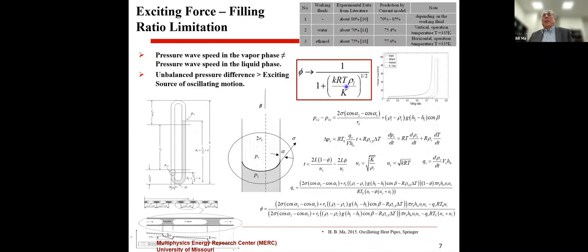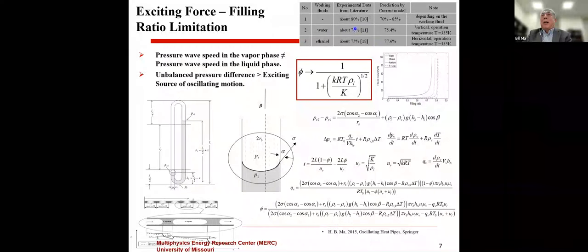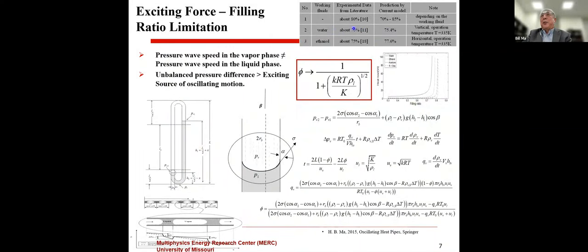What that means is that from here we can find the filling ratio limitation. Based on this equation, we can predict, for example, for a water heat pipe, if the liquid ratio of water in the heat pipe is higher than 75.4%, the oscillating motion cannot start. So here are the experiment data, basically very close to our prediction.